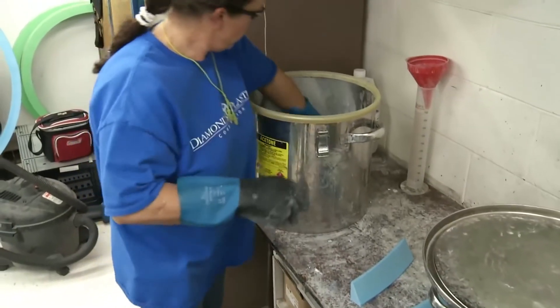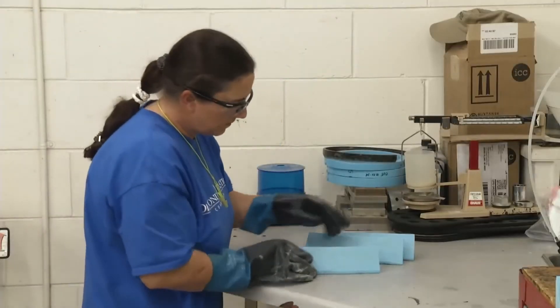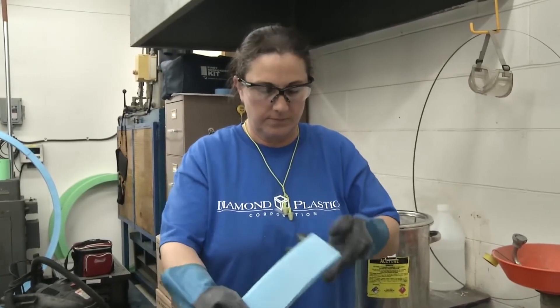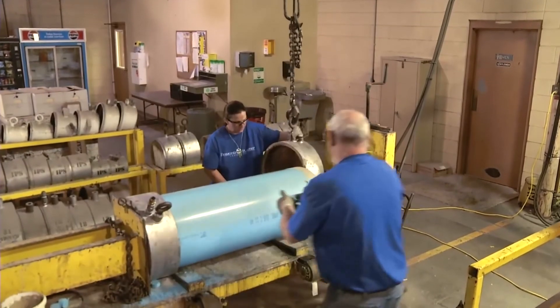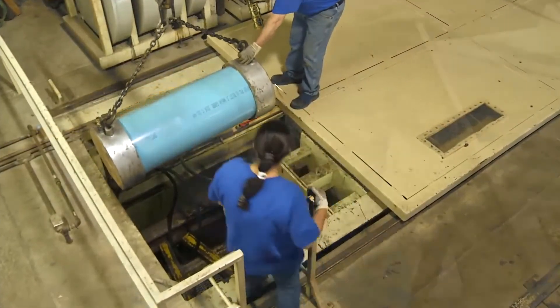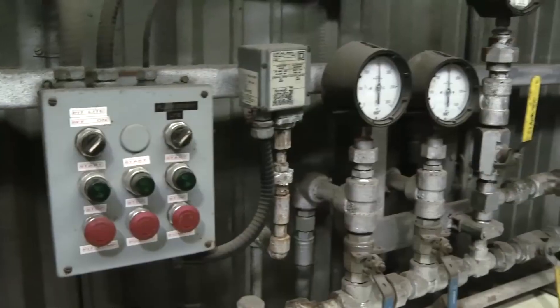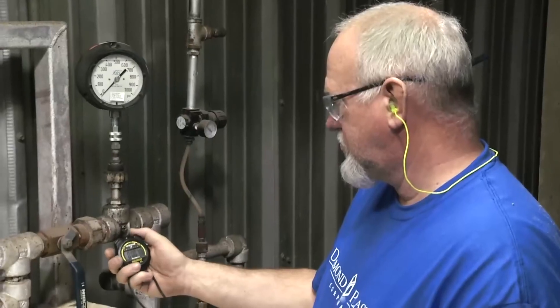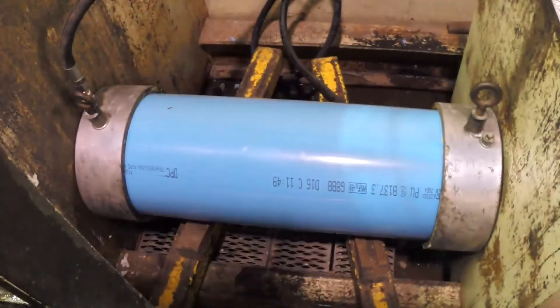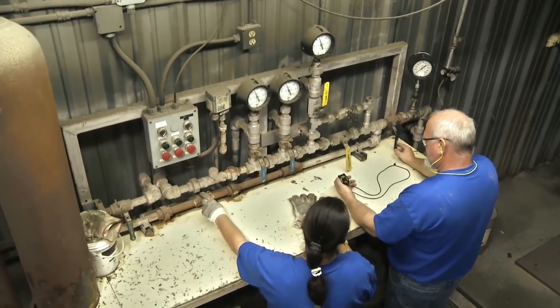A fusion test is performed by placing a properly prepared sample into an acetone immersion bath for 20 minutes. When removed, the technician looks for flaking or lifting of the PVC, which would signal a failure and suggest an improper material fusion during the extrusion process. To meet standard requirements, pipe is routinely burst pressure tested. A section of pipe is capped and lowered into an in-ground test bunker, and a heavy metal cover is moved into place. The pipe is filled with water and the pressure increases at a specified rate. For AWWA DR18 products, that pressure is 755 pounds per square inch. Pipes are required to reach these levels without failing, and internal pressures in excess of 1,000 pounds per square inch are routinely required to cause failure.